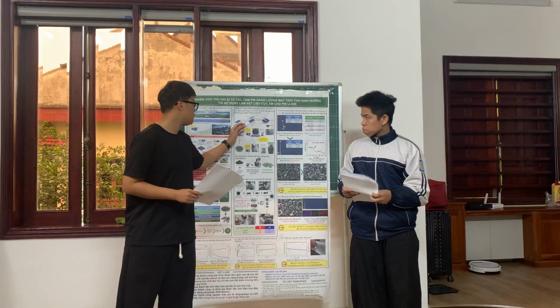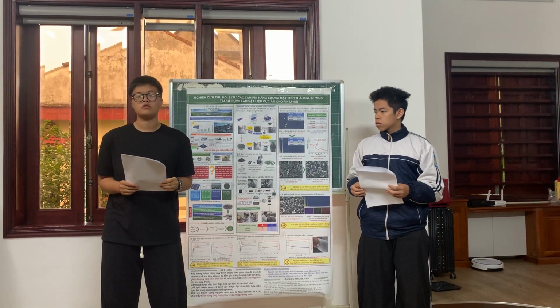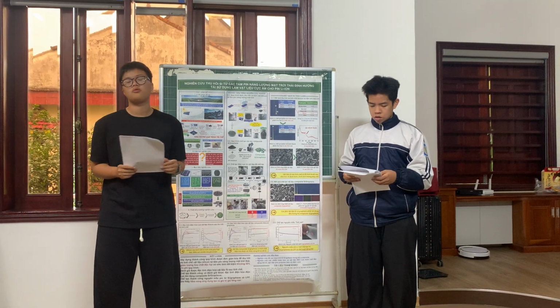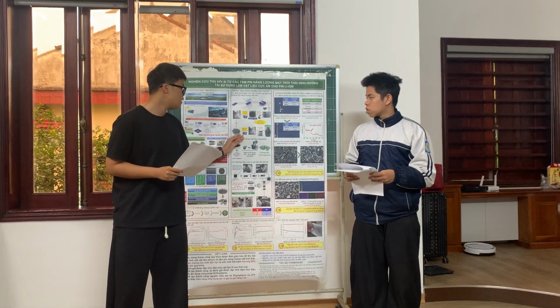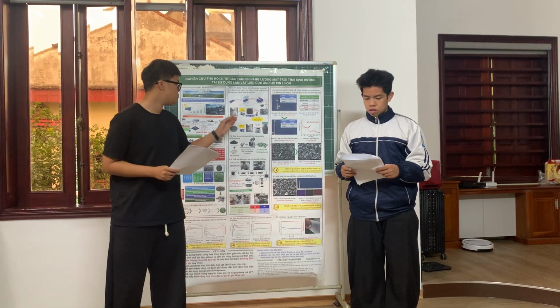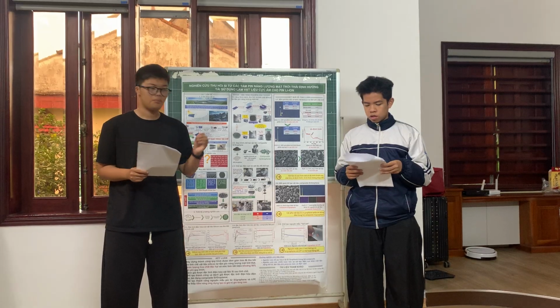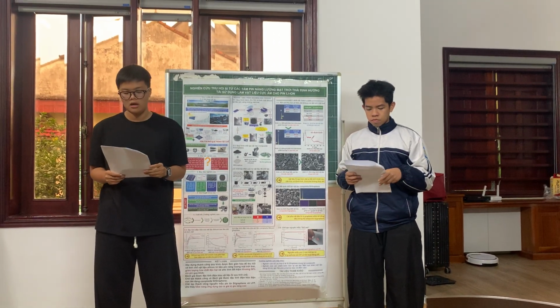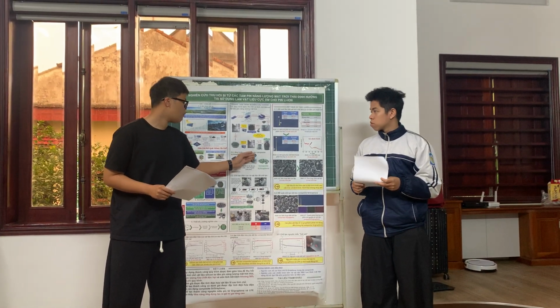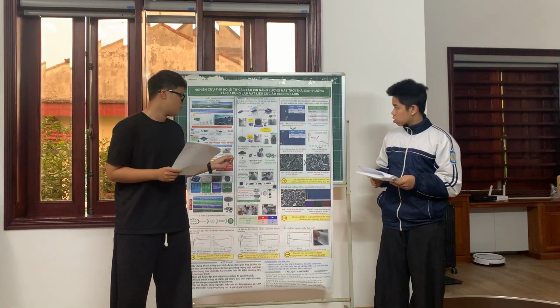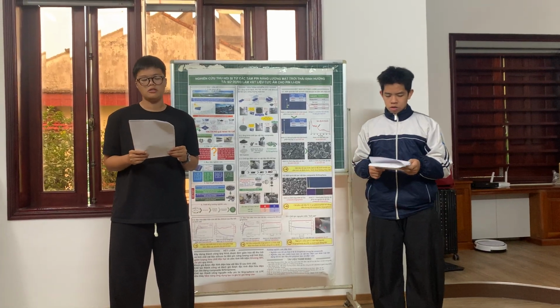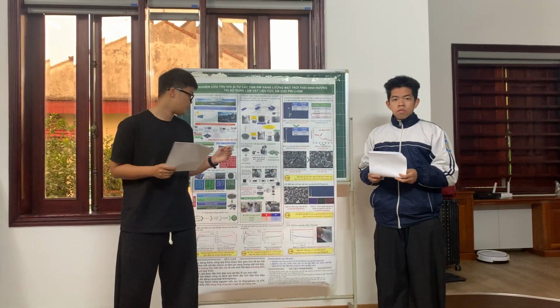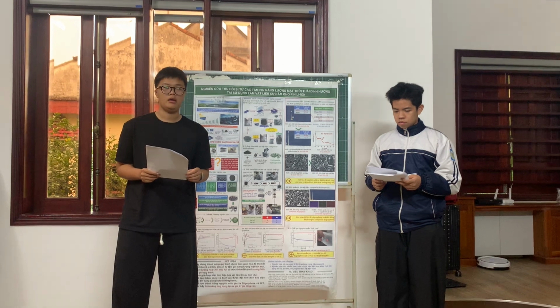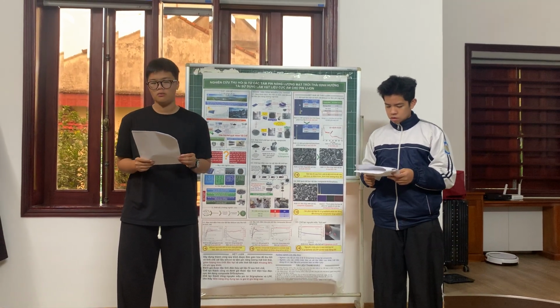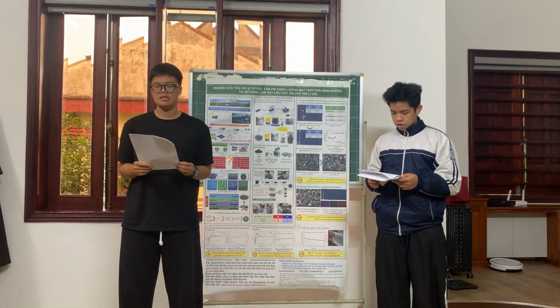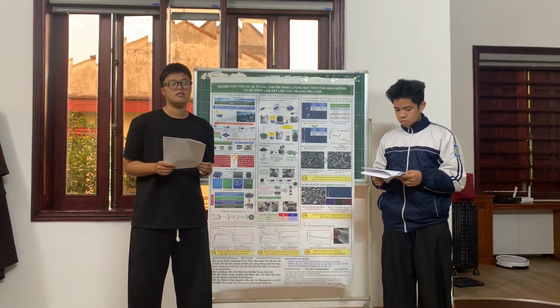First, silicon was recovered from end-of-life solar panels with a physical separation process in section 2.1, followed by a refinement process using acid and alkaline solutions enhanced with sonication. The silicon samples before and after refinement were analyzed and compared using EDX, XRD, and SEM techniques. To improve the electrochemical properties, silicon-graphene composite was synthesized by high-energy ball milling. Electrodes and half cells were fabricated following the standard process in section 2.3. The electrochemical properties were analyzed using CV, while the specific capacity and the cycle life were analyzed using GCD.